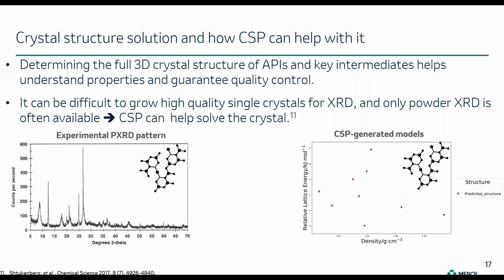It helps guarantee quality control by providing a unique simulated powder X-ray diffraction trace to be used for quality control of batches downstream. And in particular for APIs, a full 3D structural determination can be very important for patent protection. However, although single crystal X-ray diffraction is the gold standard for full 3D structural solution, it can often be difficult experimentally to grow single crystals of sufficient quality for this technique. And in these cases, only powder X-ray diffraction, or PXRD, data is available.